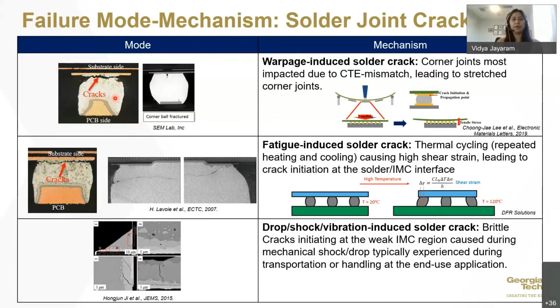Another type of failure mechanism for this crack is fatigue induced. This is more of thermomechanical stresses that are experienced by the solder joint. For example, repeated heating and cooling cycles can cause high shear strain, again leading to crack initiation and propagation at the weakest interface, which would be between the copper pad and the solder at the IMC interface.